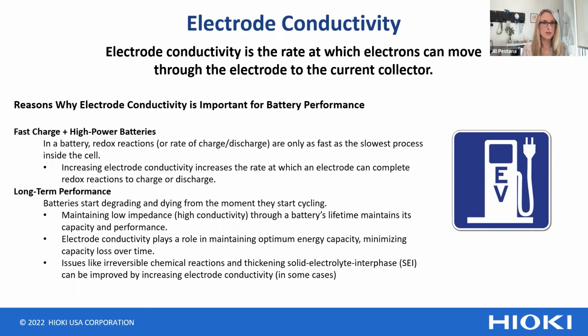The first, especially in the EV industry that I see, and in aircraft batteries too, where you need high power, fast charge batteries: in a battery, the redox reaction or the rate of charge and discharge are only as fast as the slowest process inside of the cell. And so that means if we increase the conductivity of the materials, including the electrode, we can increase the rate at which it can complete those redox reactions to charge and discharge.